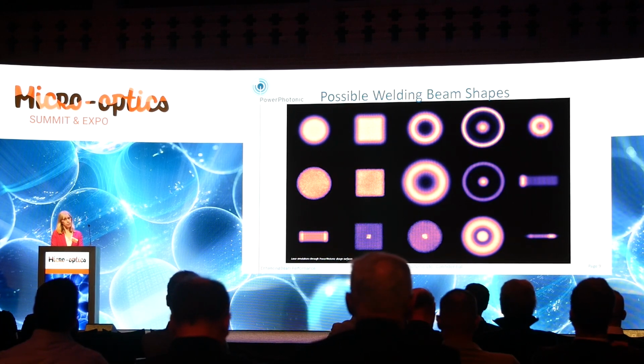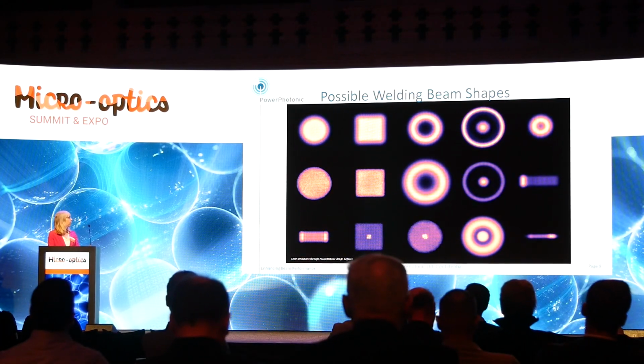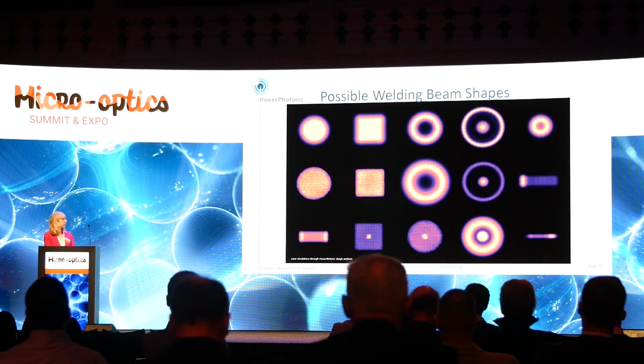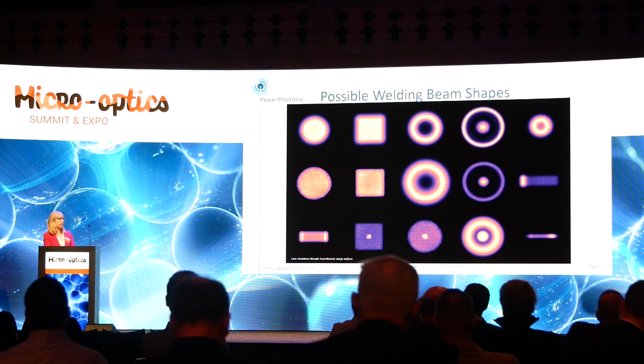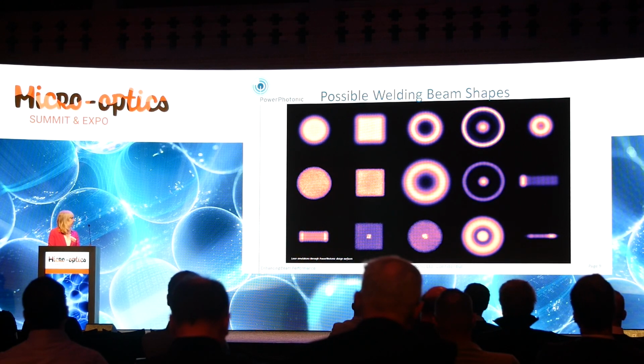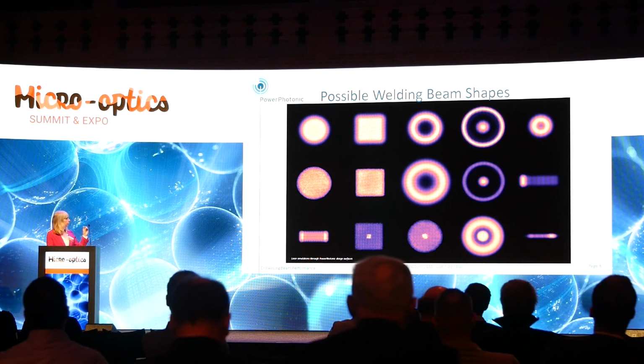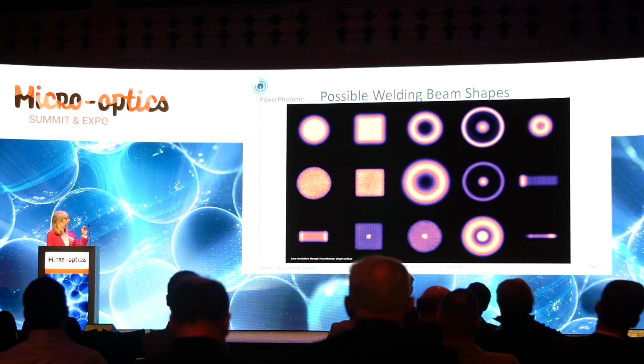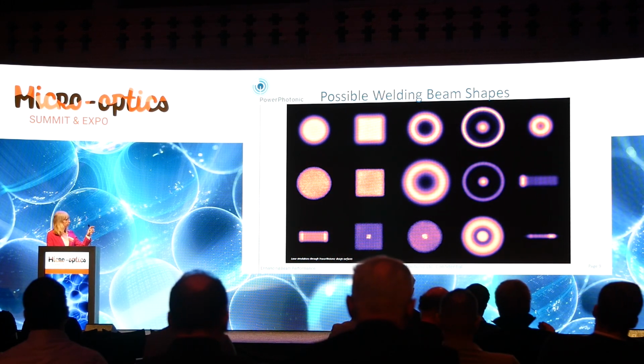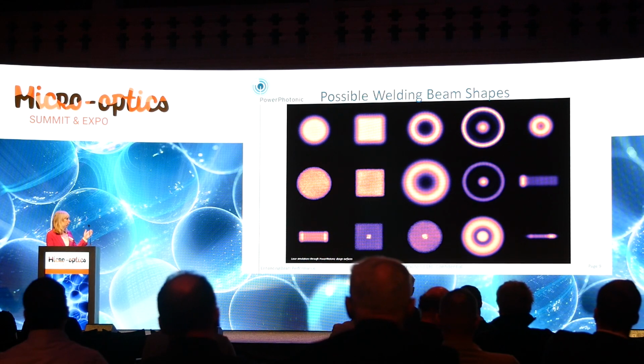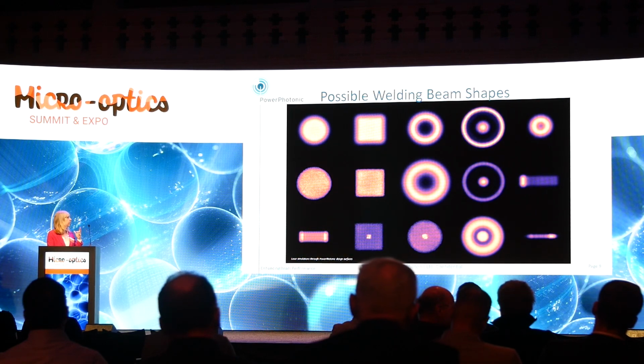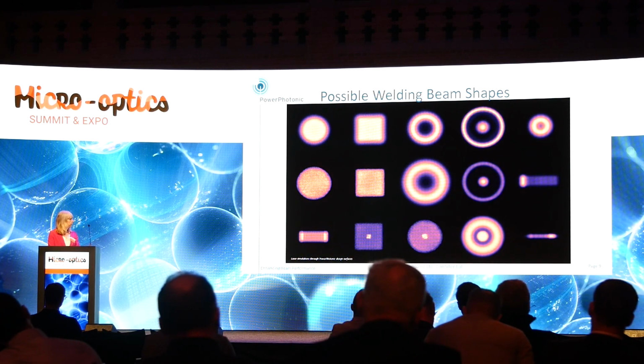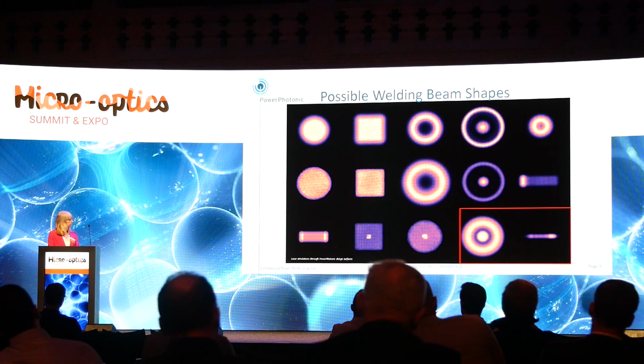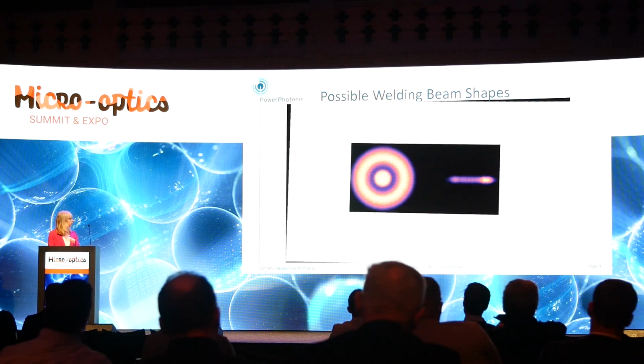Here is a little picture of our different possible welding beam shapes, thought up by Dr. Alex Griffiths. As you can see, you've got rings and cores, and you've got what we call a tail shaper, which has a hot spot at one end. You can even have hot edges. You can have a flat top with a hot spot in the middle that's square, round, and you name it. But the most important ones we're going to talk about today are the core and ring and the tail shaper.